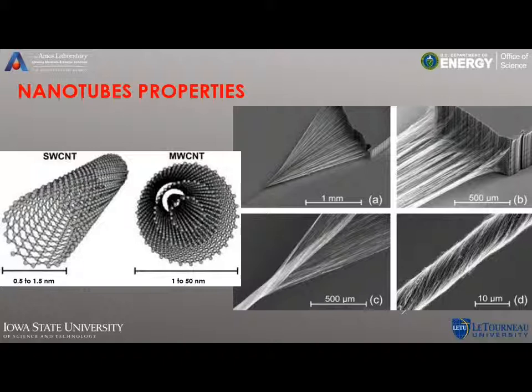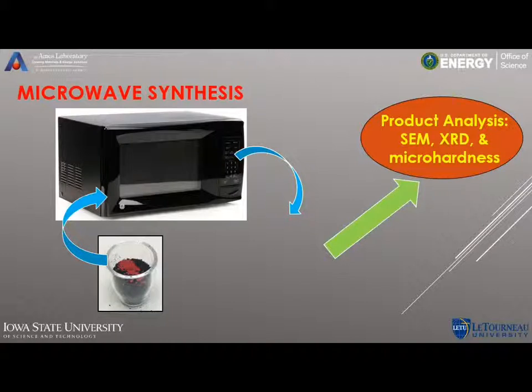But here I'll illustrate our basic procedure for making these metal matrix composites. We started out with a quartz crucible, which we used instead of the standard glassware because it has a higher thermal stability. It's not going to be as likely to fracture with a sudden change in temperature. And then we added nanotubes to that and about half filled it, and then added oxide on top. And then we just placed that in a standard microwave oven and heated it for